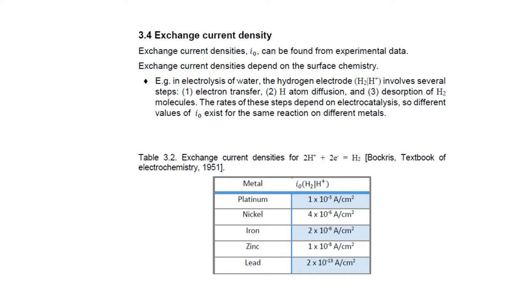Importantly, exchange current density for a process depends not only on the chemical transformation. For example, copper to copper 2 plus is one transformation, or hydrogen ions H plus turning into hydrogen gas is another transformation. Not only does it depend on that process, it also depends on the surface chemistry. How catalytic is the surface this electrochemical process takes place on? And this is very important, especially for the hydrogen reaction.